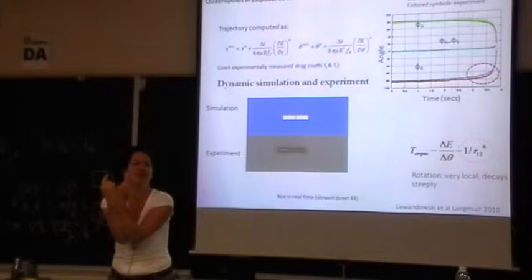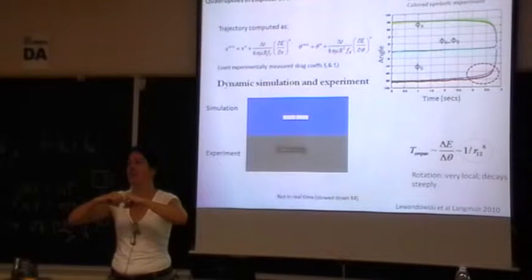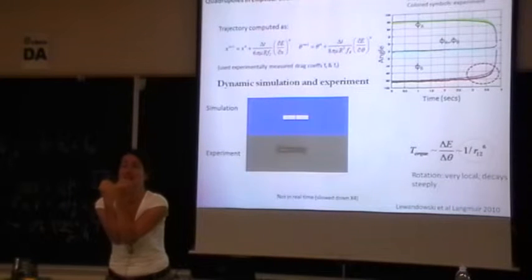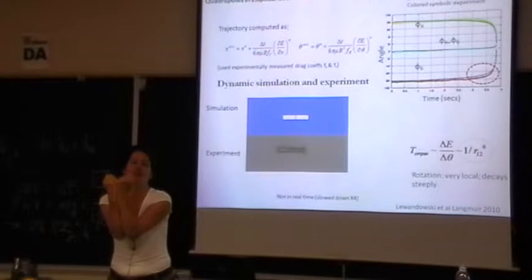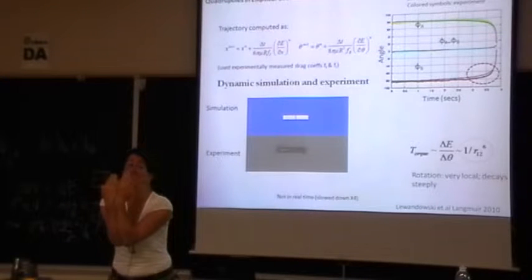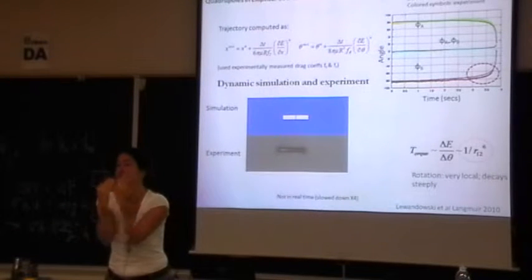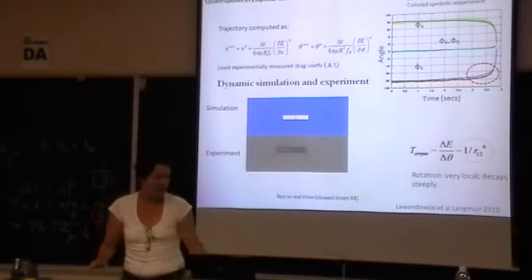And we could actually think about that right away, right? This has rise, and this has fall. If we make rise overlap with rise, slopes go down. If we make fall overlap with fall, slopes go down. Just imagine if you could lie next to each other, rise overlapping with rise, fall overlapping with fall. You get rid of a lot of area. Okay, so we won if I stop the lecture here. But then the same analysis goes side to side. So the near field interactions are telling the cylinders to be different from the ellipsoids. Sorry.